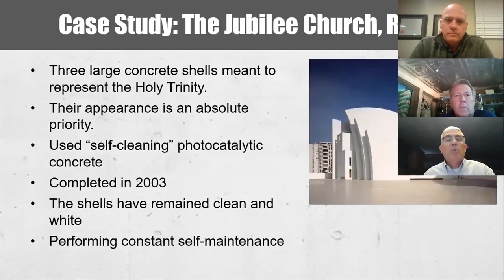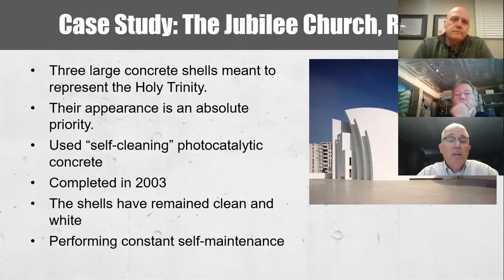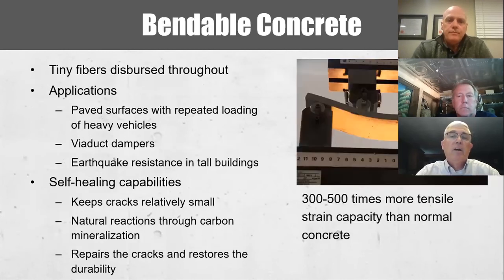And that's exactly the process that was used by Richard Meier, the architect on the Jubilee Church, to maintain the pristine, pure appearance of this design. These three large concrete shells that you see in the photo were designed to represent the Holy Trinity. So their pure, pristine appearance is an absolute aesthetic priority. And so with the self-cleaning photocatalytic concrete, this project built in 2003 is still looking as clean and as white as it did when it was first opened, because of this continual self-maintenance process that's possible with this concrete.